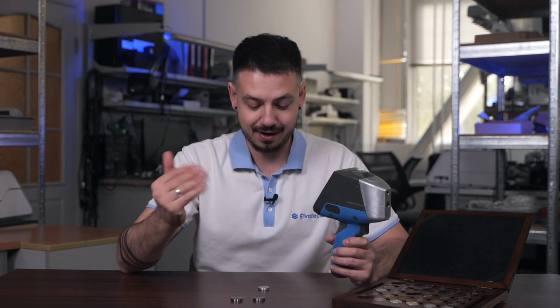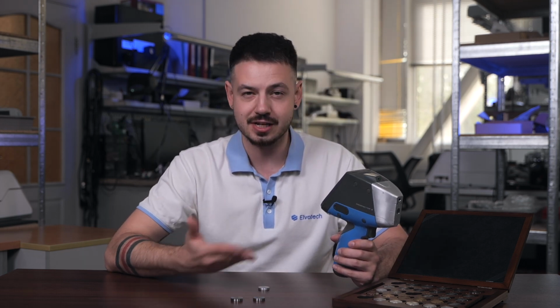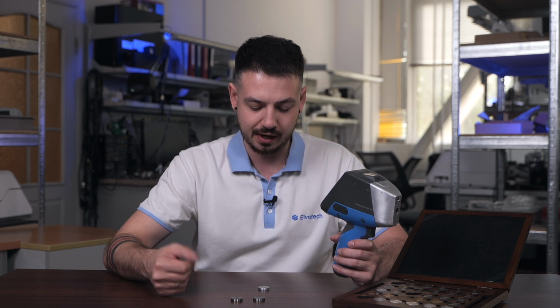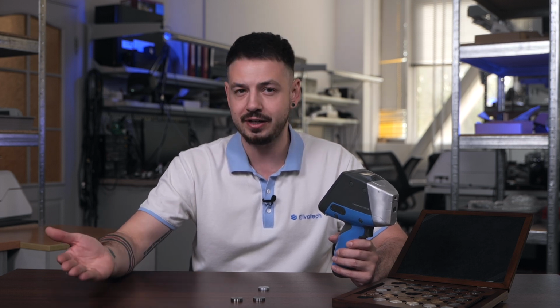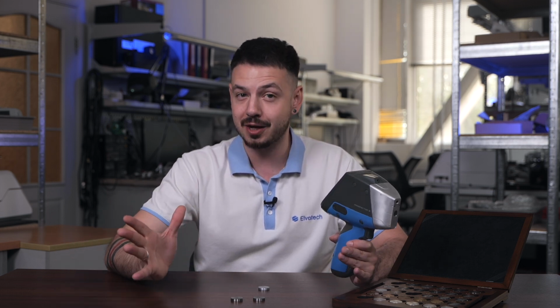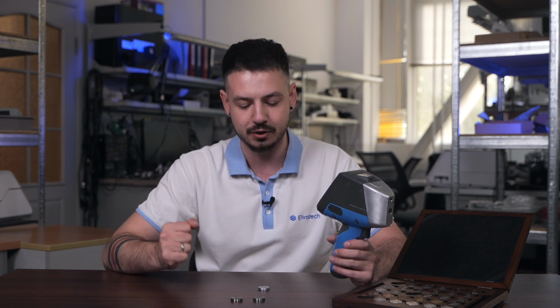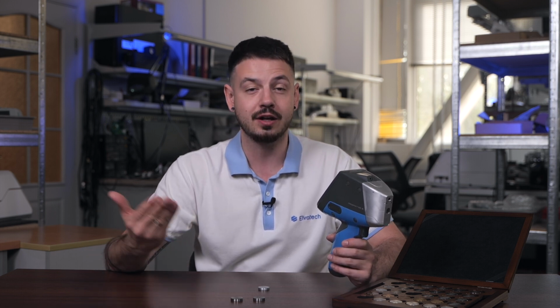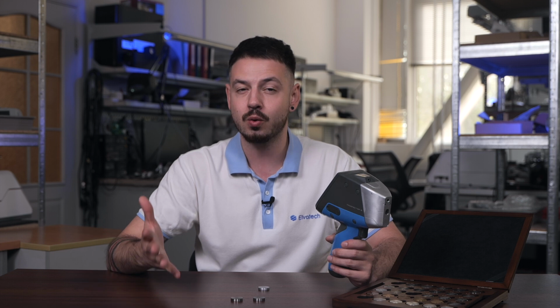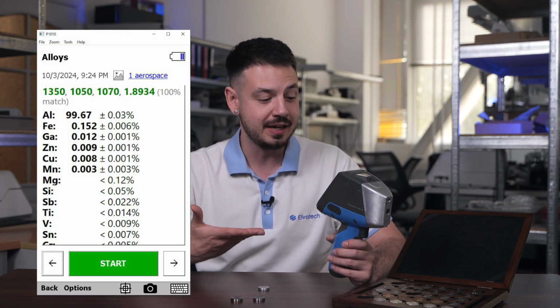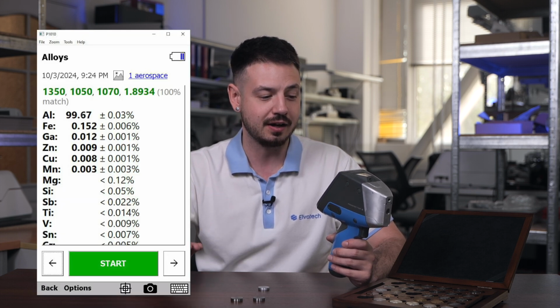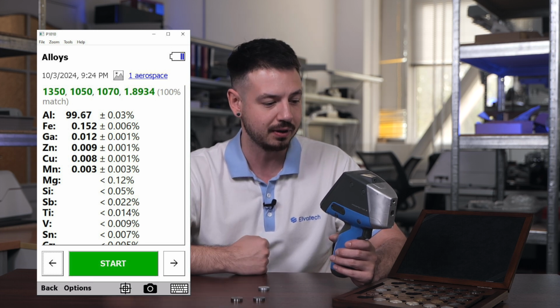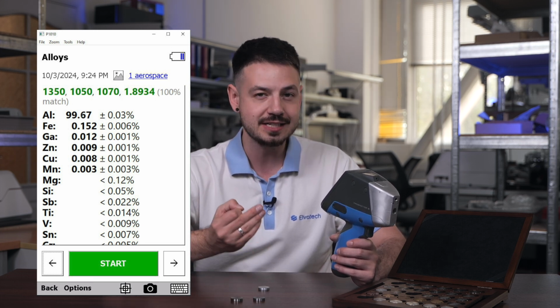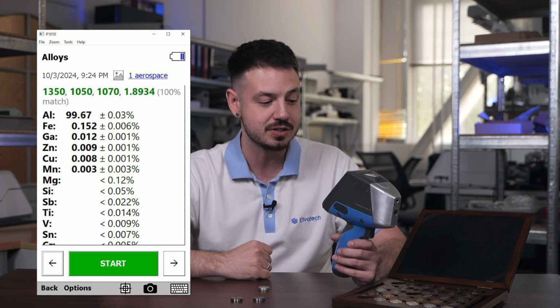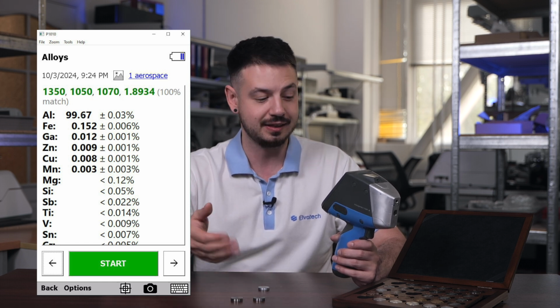Alright, so we have our first result, and this was aluminum 99.3, but the actual composition of aluminum in this sample is usually set at 99.6, so it's averaging. And we have the results where aluminum is the base alloy, the leading element absolutely in this sample, and it contains 99.67% of aluminum.